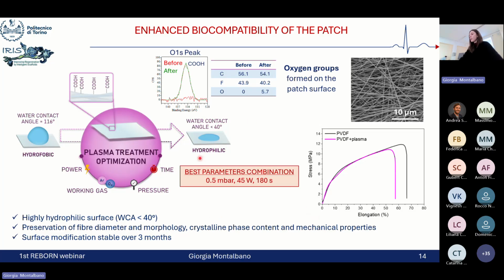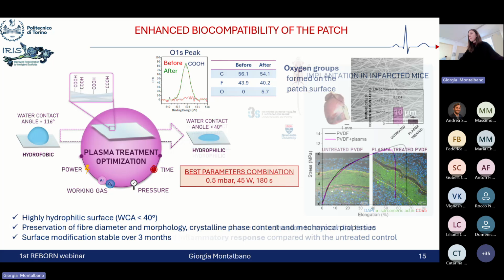And moreover, the optimized parameters were also effective in preserving all the characteristics of the polymeric patch. So we could preserve very well the fiber diameter morphology, the crystalline content, and also the flexibility, so the mechanical properties of the patch. And we also found the high stability of the process, where all these properties were preserved over 3 months after the initial treatment.